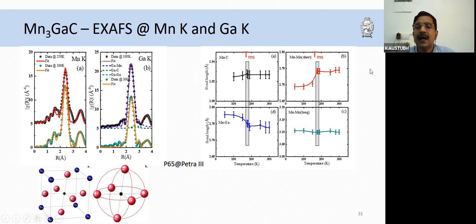across the transition. This is the manganese gallium, and it follows exactly what happens with the lattice. Below the transition, the manganese gallium distance increases in value as compared to above the transition, which is what happens with the lattice also. This distortion of the manganese sublattice created two manganese distances, a short distance and the long distance. The long distance was around 3 angstroms, and that was again invariant across the transition, whereas the short distance suddenly showed a decrease at the transition